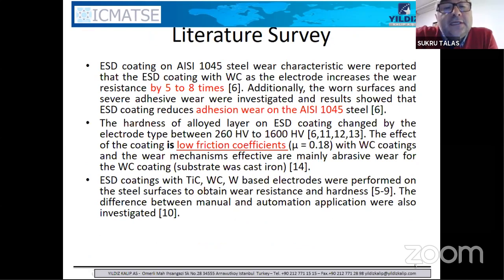Is there anything else? Yeah, we can coat the surfaces with tungsten carbide, titanium carbide, tungsten, as long as the electrode is conductive, as I mentioned before. The surface can be coated very easily with any ceramic material. It can be coated with a mixture of compounds, like titanium carbide plus titanium diboride, or titanium carbide plus tungsten carbide at the same time. This is also possible as long as you have an electrode.